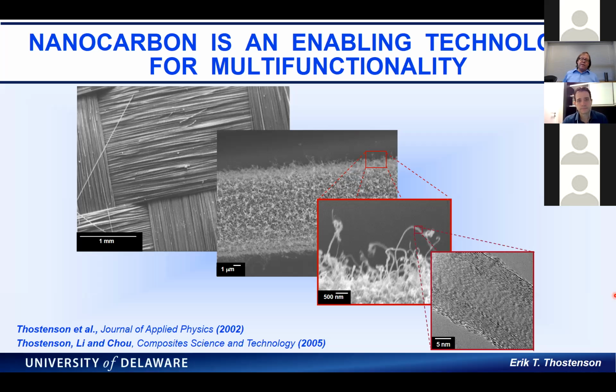Yeah. So I haven't grown nanotubes for years. We have purchased nanotubes commercially. When I was a PhD student, we bought some tubes, and they were $800 a gram. Now we can get better tubes for less than $1 a gram. And for what we're doing with these composites, we're not using a lot of material. The CVD process for growing carbon nanotubes, which is how most commercial, particularly multi-wall tubes, are made, is inherently scalable. There are companies still making them, and it's really about finding applications for them, but they're fairly inexpensive now.